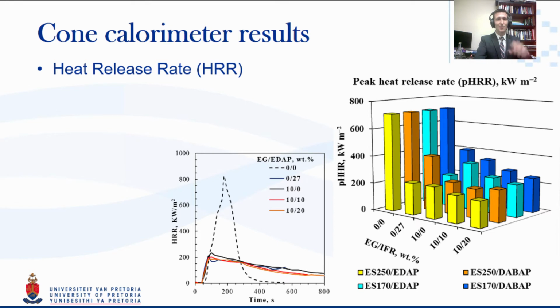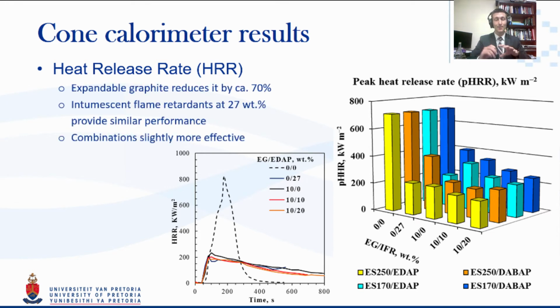So one of the things that we can see here is that it sort of moves down in a wave to the bottom, and it shows really good results in the two yellow samples, which is actually exactly what we wanted, because you'll notice that those, they say 10 and 10 and 10 and 20 next to them, are actually our combined formulations. And those formulations are the ones that are actually the most economically favorable.